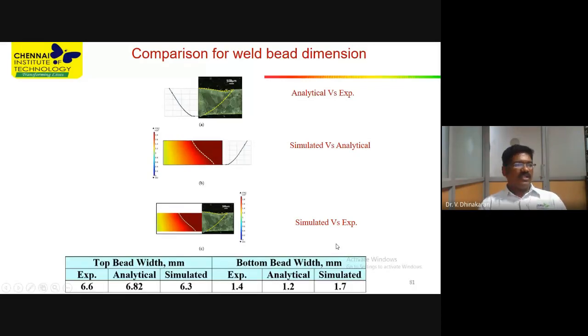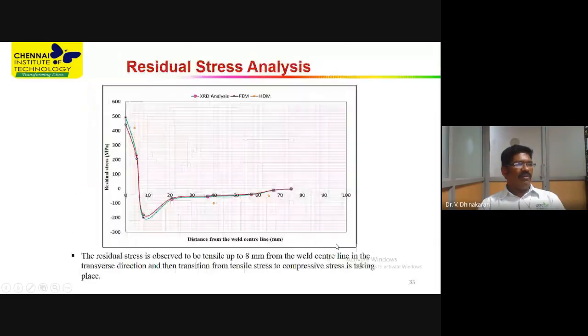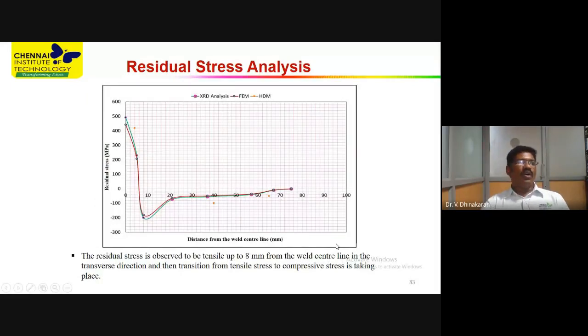Computational mechanics will be highly useful to eliminate the number of experiments, and see the results such as the experimental XRD analysis and FEM and hole drilling method. The FEM method, the computational method, is on par, predicting the results with the XRD and hole drilling. Okay, so this is the residual stress measurement, and I want to wind up fast within 5 minutes.